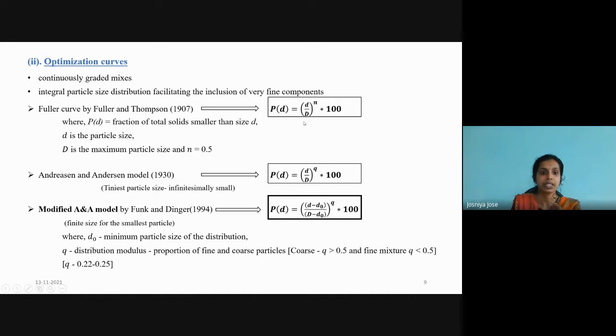So they developed an equation, and further improvement was done by Andreasen and Andersen, where they included a distribution modulus, the Q term, which defines the proportion of fine as well as coarse particles. So if the matrix is a coarse matrix, then adopt a Q value greater than 0.5, and for a fine mixture, a Q value less than 0.5 is adopted. And this Andreasen and Andersen model considered the smallest particle to be infinitesimally small. But in practice, we know that even the tiniest particle has a definite size.